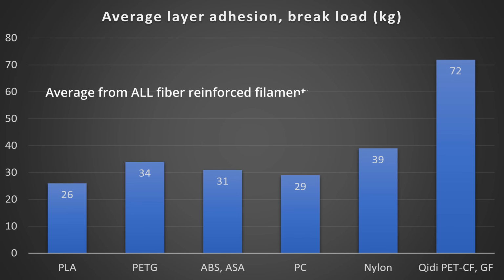It is a great material, fantastic mechanical properties. Of course it requires higher printing temperatures, but this is not a problem for today's 3D printers. And this layer adhesion, it's fantastic. Here is one graph I collected. These are all filament types reinforced with carbon or glass fibers. And here you can see how outstanding the layer adhesion is with the PET-CF and GF.